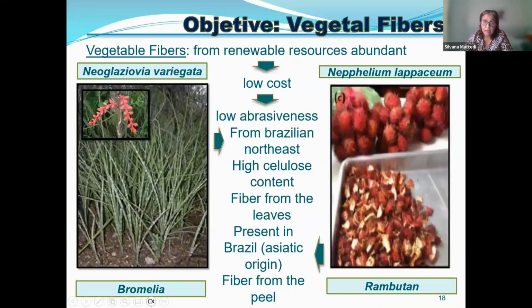We use different vegetal fibers. We use bromelia, Neoglaziovia variegata, that is from the Brazilian Northeast, which has a high cellulose content in the leaves. Also, we use rambutan that is present in the Northeast as well. The fiber is in the peel. We use the peel, not the fruit, for obtaining the fiber. And we also obtained, but in the traditional manner, so we're not showing it here, lignin from the peel.